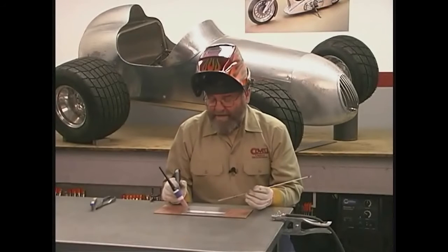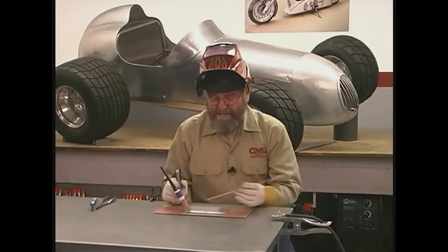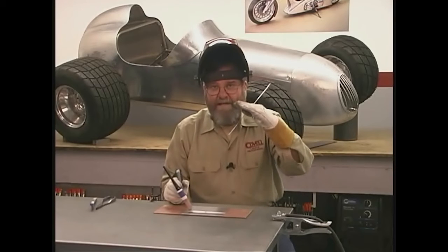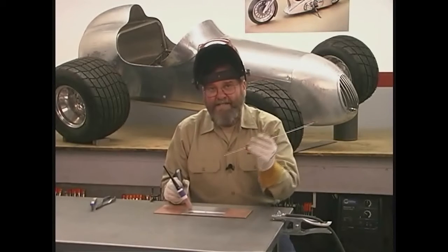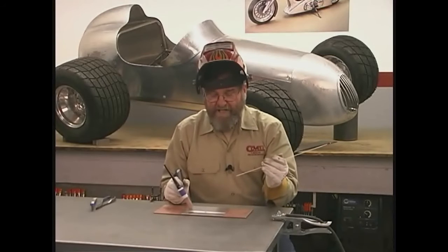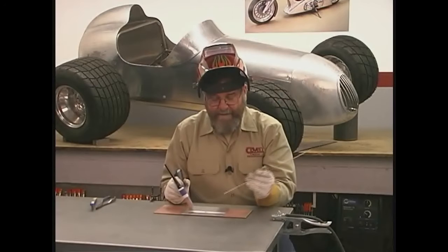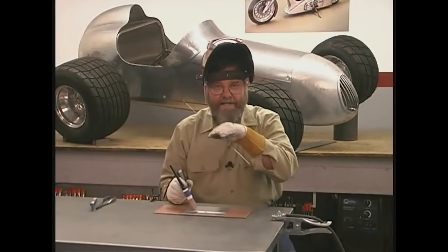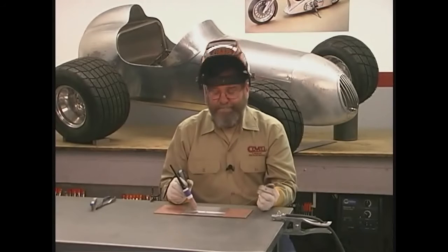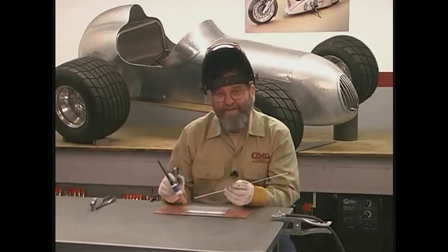Okay, now I'm ready to make the weld. Now aluminum has some special considerations. As I approach the end of the weld, I have to do things a little bit more carefully. First of all, I'm going to get off the heat rather slowly, and I'll be adding filler rod as the puddle diminishes in size. And then just before the arc is extinguished, I dip the rod one last time and then ease off the foot pedal. The result of this is that I can eliminate a shrink crater, which I would otherwise have at the end of the weld. And a shrink crater is an easy place for a crack to start. So this technique of slowly bringing the heat down and adding filler rod right up to the last minute is really crucial on aluminum. So let's get some pre-flow going and we'll start the weld.